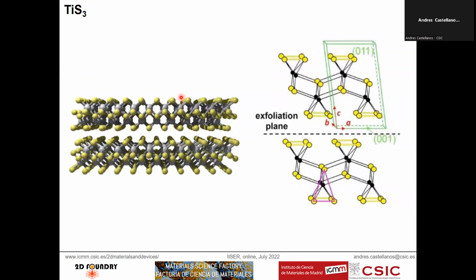But if you take a look more carefully at the structure, not the 3D, but this simplified structure, you get these chains of titanium trisulfide that go out of the screen. And these chains interact with each other by these sulfur-titanium bonds here. So basically you have one chain, another chain, another chain, and then you have these interchain bonds here. And that makes the layer. Then the layers interact with each other by just van der Waals forces, because basically you don't have any dangling bond here. And therefore you just interact by van der Waals forces, making these stacks.